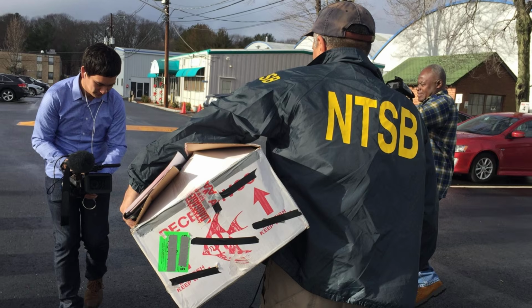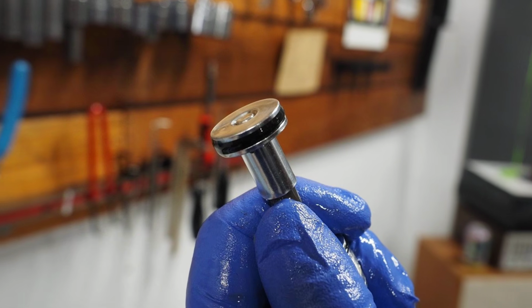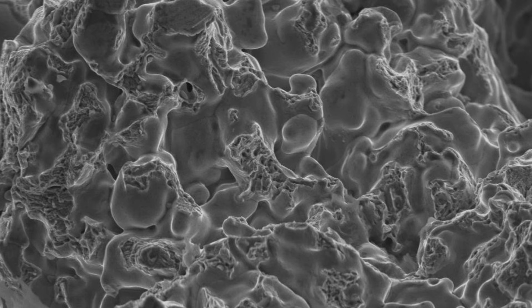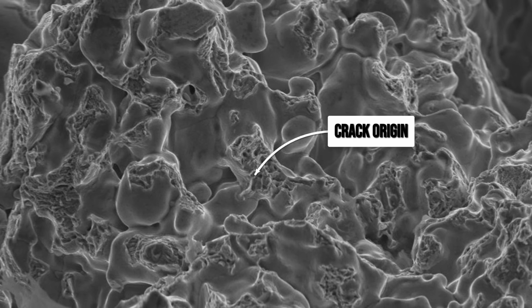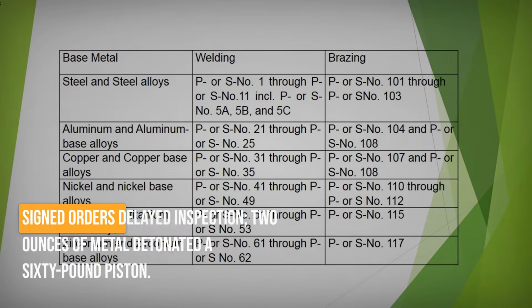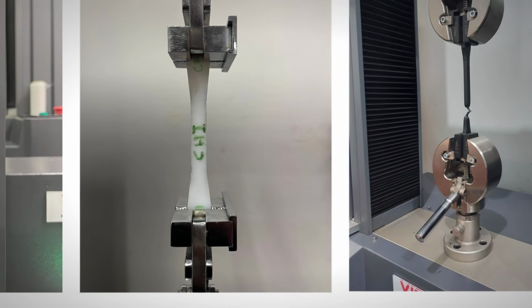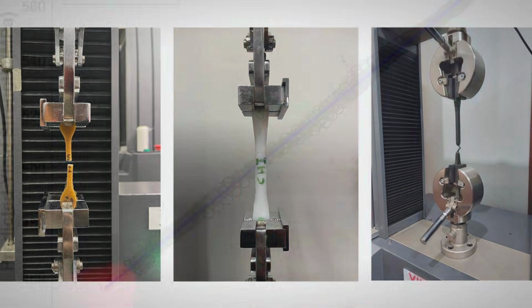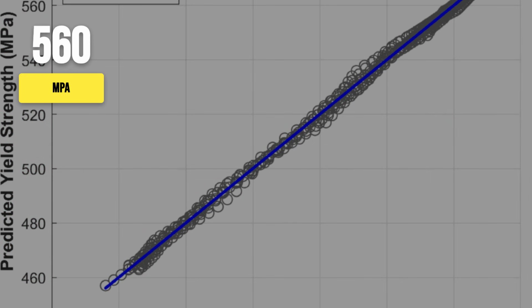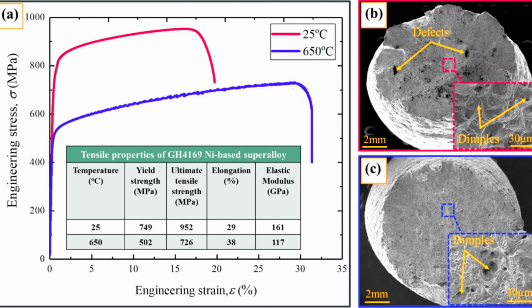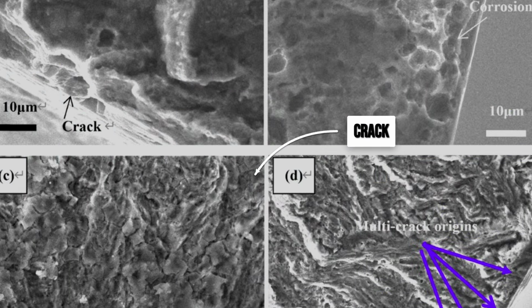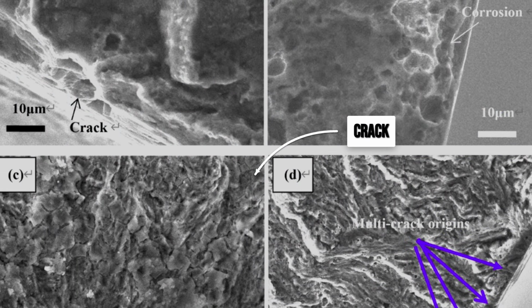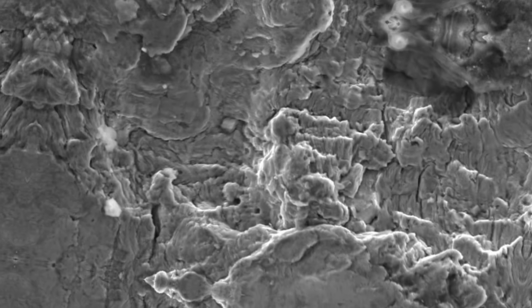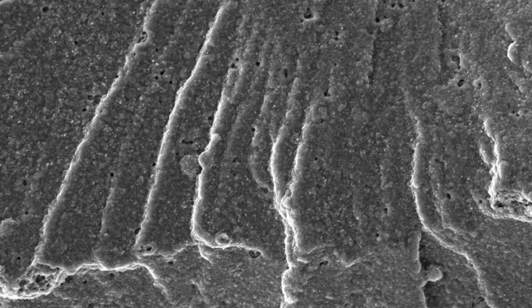The evidence begins with the chain of custody log. A 2-ounce valve keeper tagged and photographed in the shop, its fracture surface exposed beneath the harsh glare of the lab micrograph. The keeper is a high nickel, 18 chromium molybdenum steel, specified at 1,100 megapascals tensile yield. The measured yield after failure was 560 megapascals. The metallurgical report labels the fracture origin as classic high cycle fatigue, propagated from a pit at the seat retainer interface. The micrograph shows striations radiating outward like a clock running out of time.